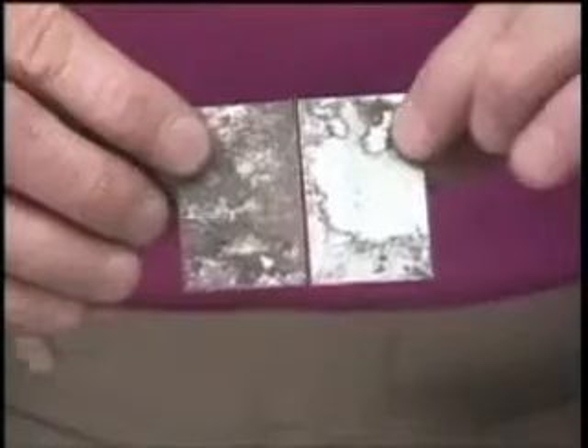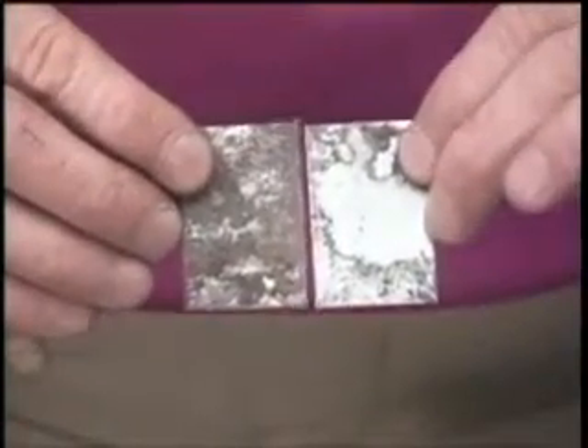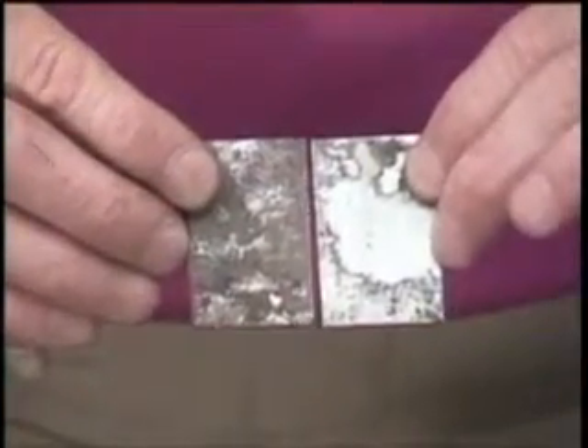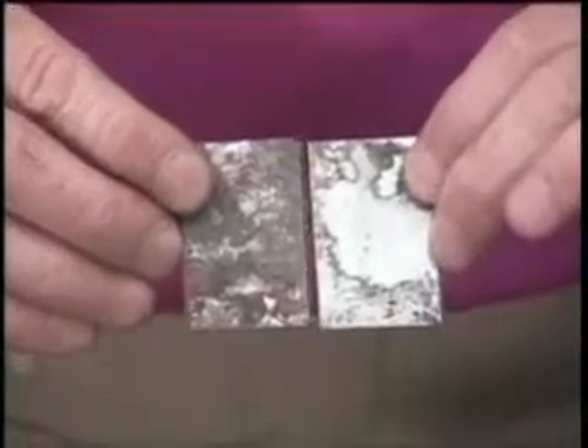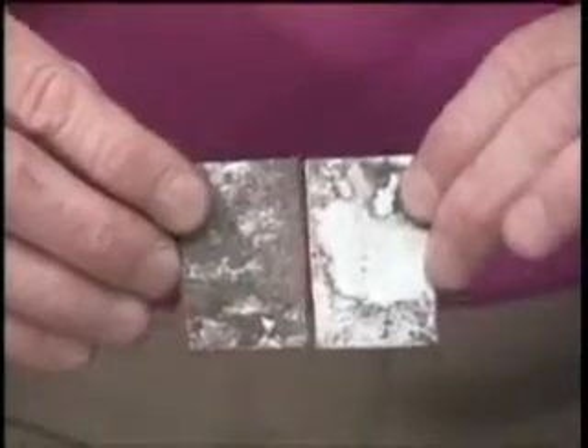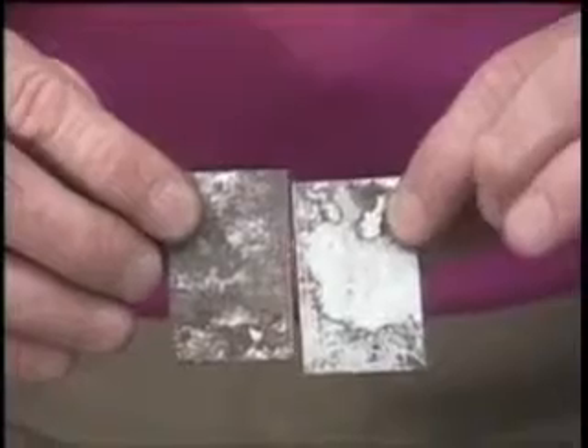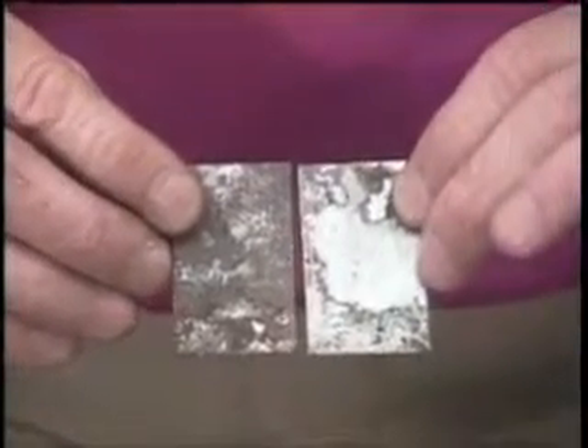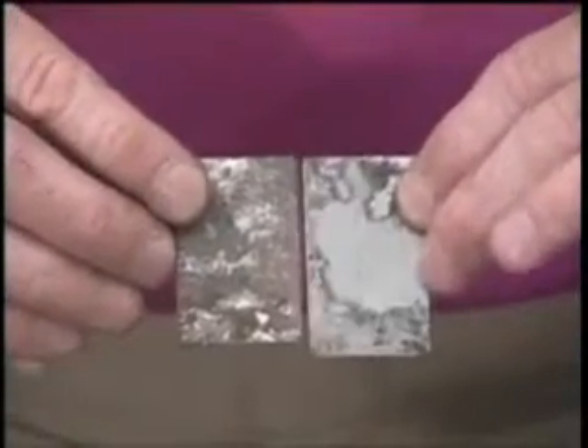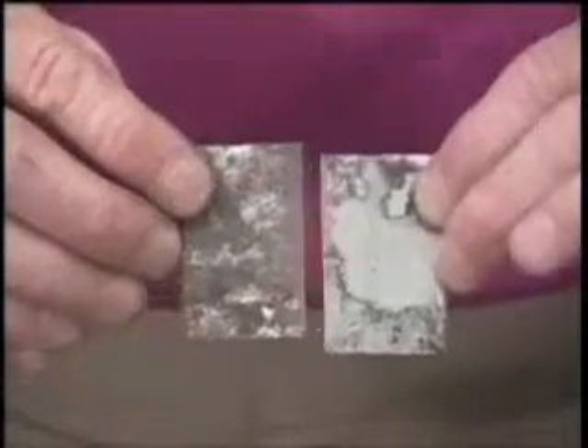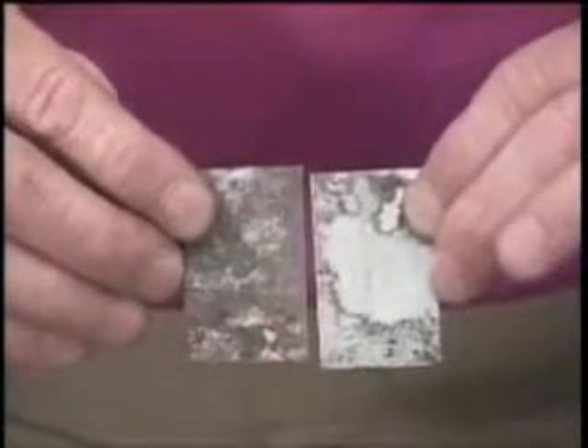Now, remember, the great thing about oxyacetylene, especially if you're worried about distortion, is if you get any distortion because it is an oxyacetylene weld, you can actually hammer weld it out. It's a soft weld. For a lot of guys that are using the TIG or the MIG, it's what they call thermal shock in the metal. As you go in there and get distortion, you cannot come back and move that metal. It's a very rigid weld. That's when you got to come in there with your Bondo.